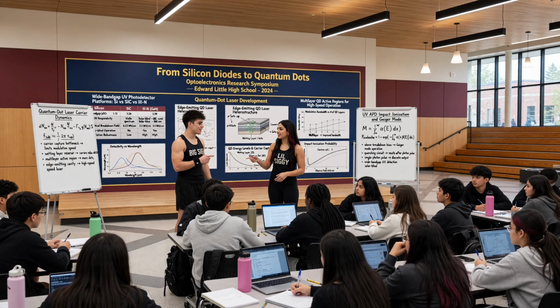But the inefficiency isn't even the worst part. There's a much darker reality for silicon when exposed to UV. The energy of those UV photons doesn't just fail to be detected. It actively destroys the sensor over time. It is a severe reliability issue. Those ultraviolet photons pack so much punch that when they smash into the surface of the silicon lattice, they have enough energy to literally break the covalent bonds holding the crystal together.